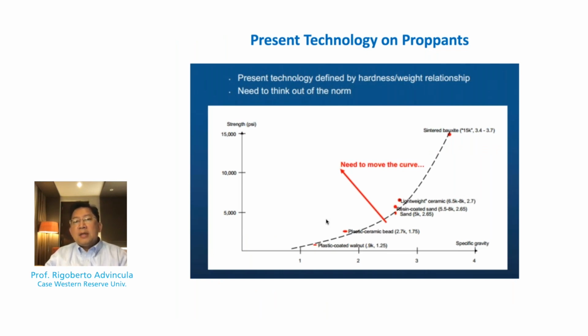So having said that, let's look at some basics here. One of the difficulties in maintaining the ability to transport a proppant is specific gravity or density. So typically, the fluid itself, hydraulic fluid, is of a lower density. Sand and resin-coated sands have a lower density. However, particles like bauxite or ceramics have a high density. In other words, the specific gravity tends towards the value of 4, whereas your fluids typically have a value of 1 or 1 to 1.5. So the question is, what happens to a proppant when you suspend it with a viscosifying fluid? The answer is, if it has a higher specific gravity, it has a tendency to settle, or as a suspension to settle or separate from the viscosified fluid.